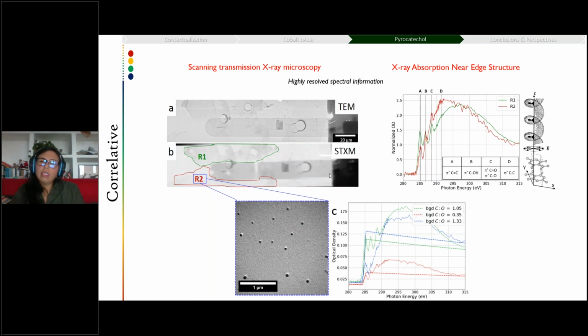And we were able to see the different ratios of carbon and oxygen throughout different regions of the electrodeposited film, and that this material effectively has carbons that would correspond to graphitic materials, as we are thinking at the moment. So this shows the power of using the exact same sample with different techniques, because this is the exact same chip that we took to the synchrotron and observed with the different techniques.